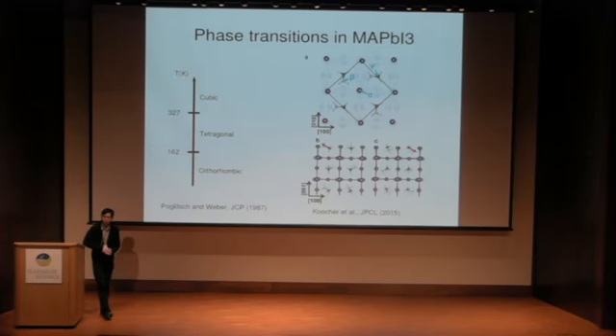Do you know the exact space group at room temperature of this compound? Because the previous talk showed that there was like Pnma, I4/mcm, and Pm3m, which are all centrosymmetric space groups. Since it's been shown that the BPVE, for instance, is a fourth-order tensor, it should vanish in this case because there is central symmetry. So do you know the space group of this compound?